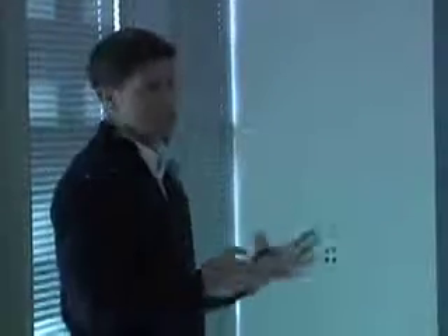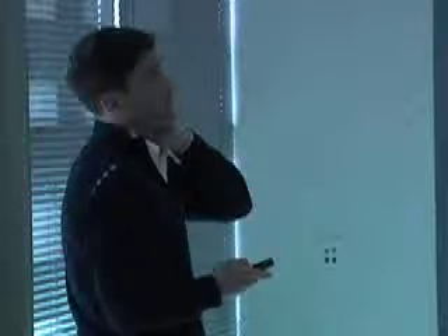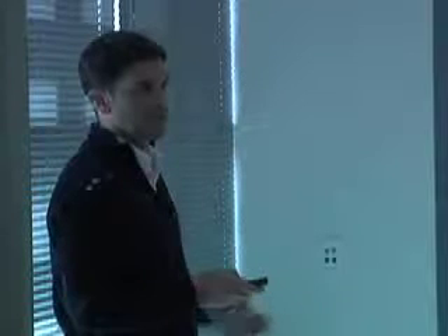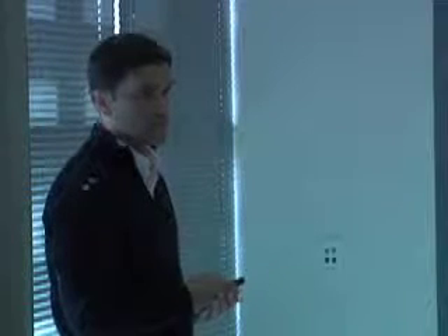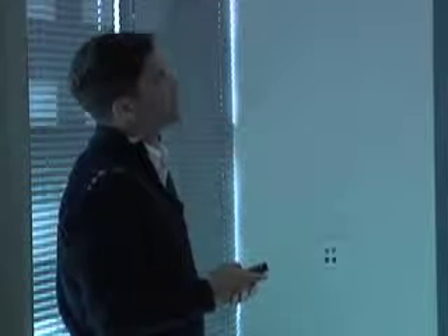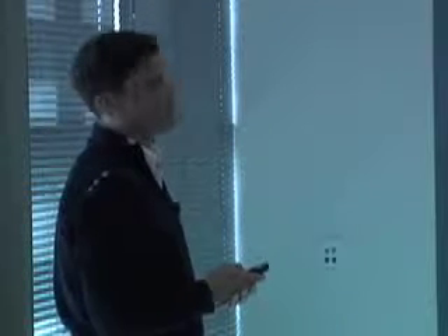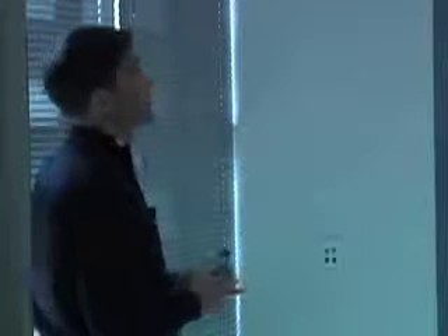This is work that we kind of stumbled upon. So we had been making low band gap dyes for dye-sensitized solar cells. And it turned out that one of the byproducts of this process, actually the chemist who did this was Bogyu Lim. He was actually here as a postdoc with Fred Wudl, and then he came to my group at Stanford. And so he had this material, and he just gave it to the grad student and said, just sprinkle a little bit into your PCBM P3HT, and it's incredible what happened, and I'll show you.